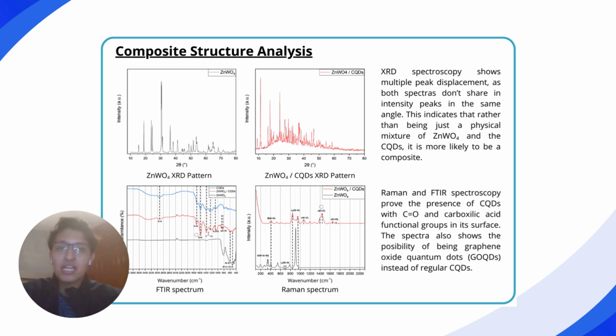Now, similar conclusions can be drawn from the Raman spectra, as the main tungsten with oxygen peaks seem displaced and/or split into other smaller peaks in the composite spectrum.